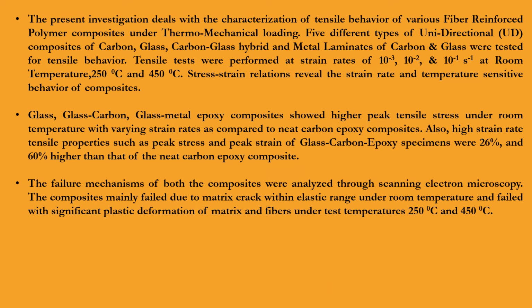The present investigation deals with the characterization of tensile behavior of various fiber reinforced polymer composites under thermomechanical loading. Five different types of unidirectional composites of carbon, glass, carbon glass hybrid, and metal laminates of carbon and glass were tested for tensile behavior. Tensile tests were performed at strain rates of 10^-3, 10^-2, 10^-1 per second at room temperature, at 250 degrees Celsius and at 450 degrees Celsius. Stress strain relations reveal the strain rate and temperature sensitive behavior of composites.